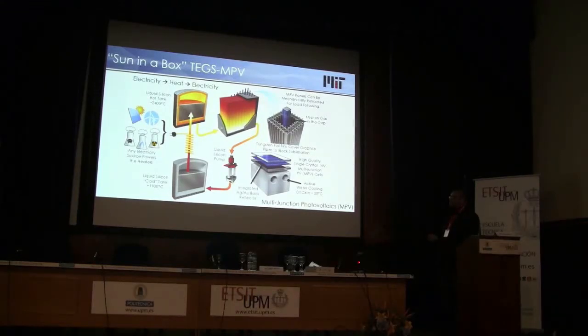So our cold tank is actually at 1900 degrees C, and we're pushing the temperature as high as possible, up to about 2400 degrees C on the hot side. Of course, when you want to store electricity, you pump the quote-unquote cold silicon, which is far above its melting point, through a heating element or past Joule heating elements. You can take electricity from any agnostic source, heat up the silicon, and put it in the hot tank. The idea here is that 2400 degrees C is more of a practical limit. The entire infrastructure here is envisioned to be made out of graphite. 2400 degrees C is probably the approximate practical limit for how far you can push graphite before two things happen. Above about 2500 degrees C, the strength of graphite starts to decrease. It's actually increasing up to about 2500 degrees C. The second thing is that the vapor pressure of graphite starts to become very substantial at these temperatures. And so those are the two reasons we stop nominally around 2400 degrees C.